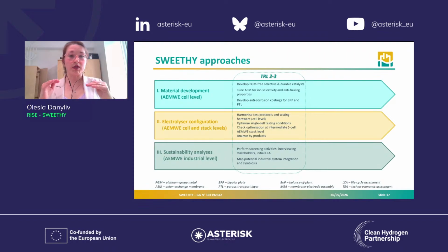Then when we go to the approach for electrolyzer configuration, we are looking at optimizing the single cell testing conditions so that all the partners are doing the single cell testing with the same conditions. We are also stepping from the single cell level checking of our newly developed materials to the intermediate stack, which is a 5-cell stack. We will also analyze byproducts during all this operation on the cell level and on the